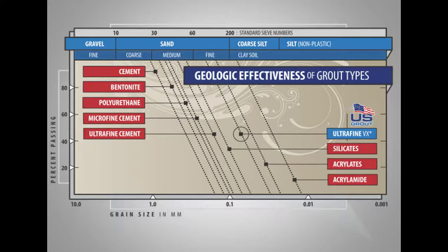Here we have a great visual that puts the particle size of various grouting materials into perspective. As shown here, ultrafine can be used to permeate most soils that have at least some type of porosity. The generally accepted guidelines being a sieve analysis on the soil that indicates at least 20% passing the minus 200 or the 75 micron sieve. Much less than that, when you start to get into clay-type soils, which are usually not amenable to any type of grouting. As you can see from the chart, OPC will grout to a certain extent, then we move to the ultrafine cements, and finally, for the toughest jobs, we move to the acrylates and the acrylamide grouts.